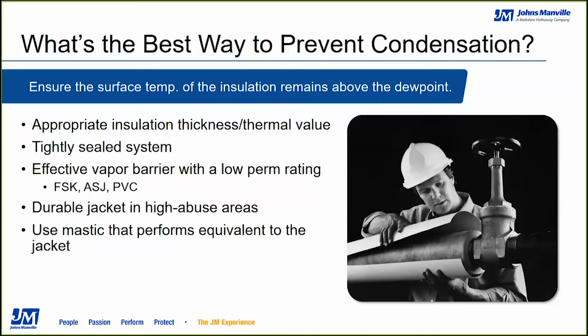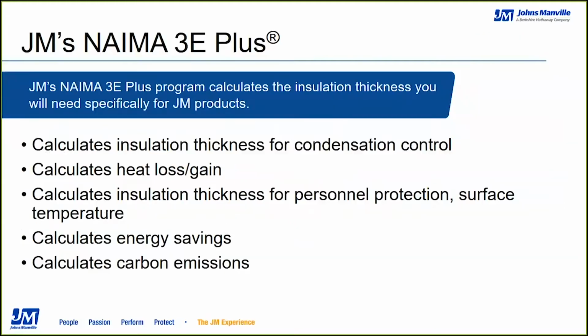For a high abuse area where there's an opportunity for the vapor barrier to get damaged, some sort of jacketing is recommended, like a PVC jacketing or perhaps a metal jacketing. And mastics are very often used to help seal up the system and any imperfections. And you do want a mastic that has a very good perm rating as well, at least below 1, but you can get them as low as 0.02, similar to the jacketing.